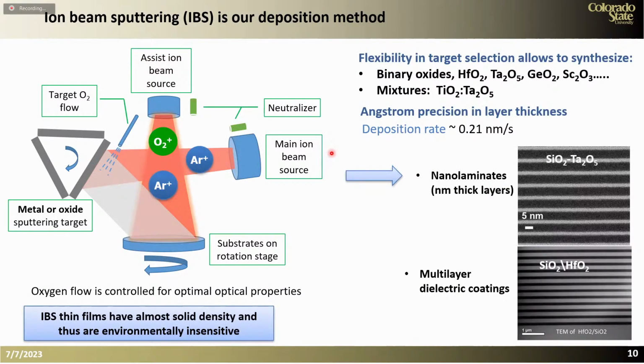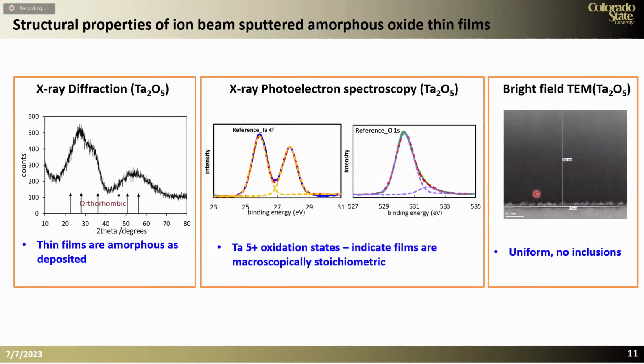Now we deposit our thin films by sputtering, and I show schematically here the system that we use. We normally sputter a metal target in a reactive oxygen atmosphere. These instruments have extreme precision to define layer thicknesses, and we can grow multilayers, or we can also grow nanolaminates, which are essentially nanometer thick intercalating layers of 2 oxides. We characterize our films by different methodologies, and especially what we are interested in is to identify that we don't have any crystallization, and we also investigate their bonding structure.